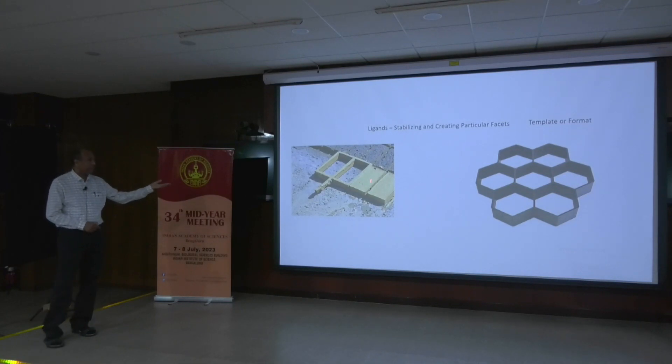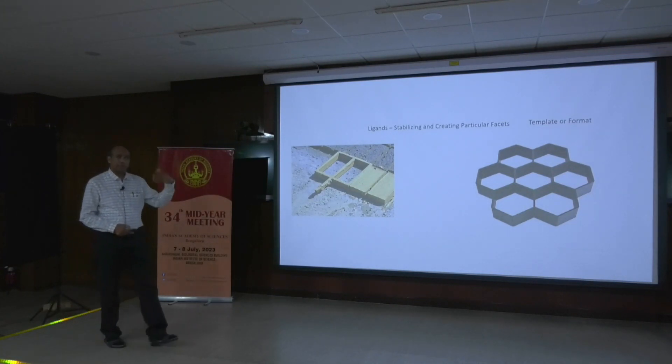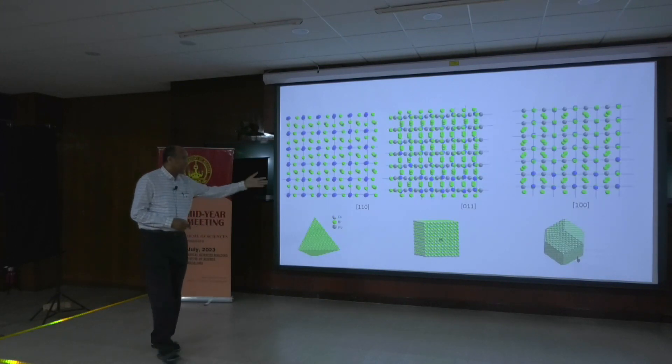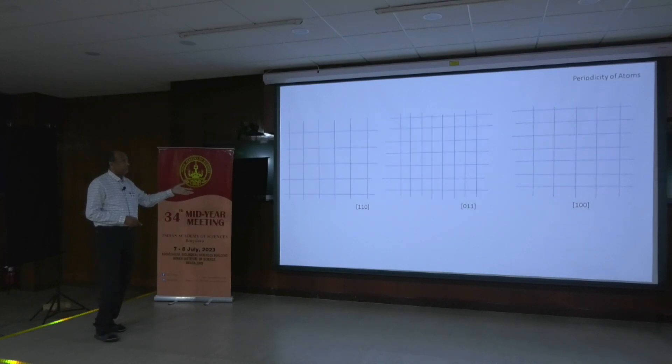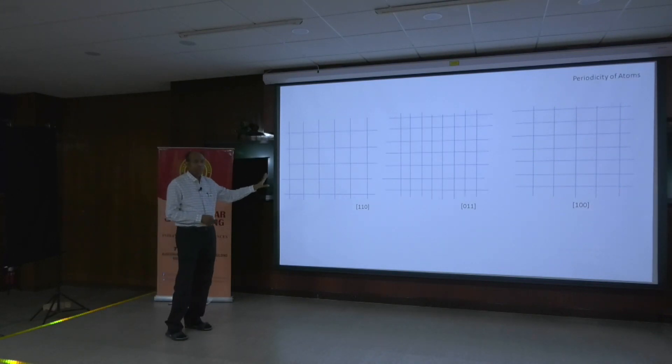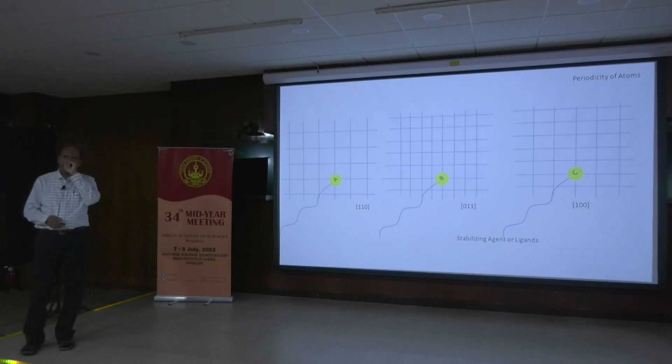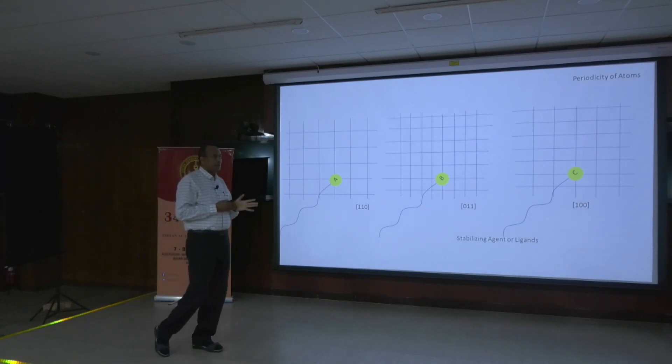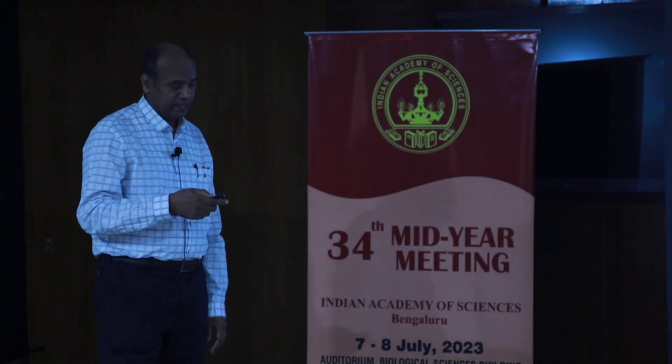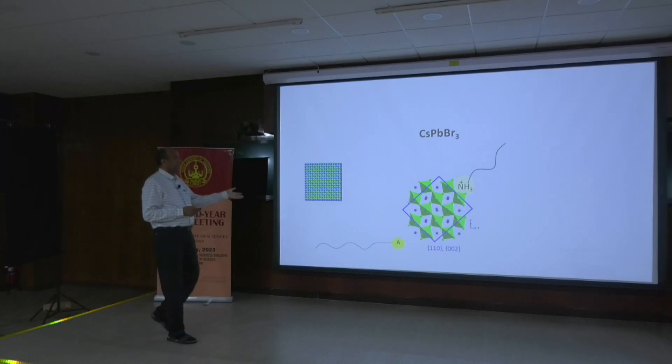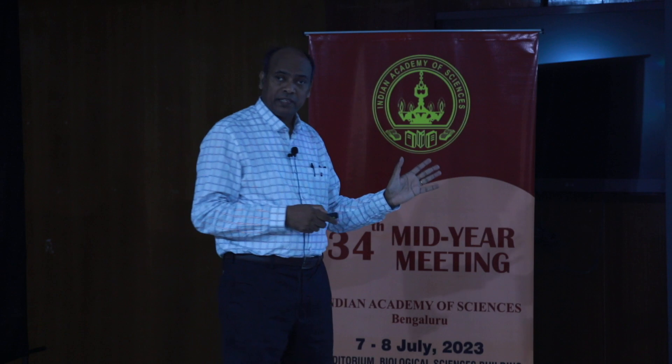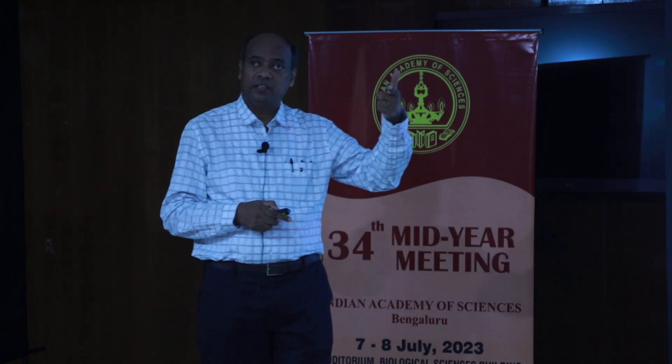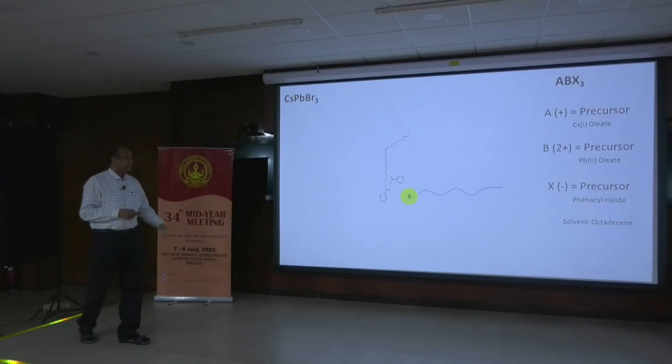It is simple. The ligands can be designed to give different types. I have taken out three facets, and I am taking just the skeleton of the covalent system, the lead one. I am preparing ligands in different sizes. But in contrast to existing nanosystems and quantum dots, these are ionic, but the surface is positively charged. The ligands are positively charged, not like zinc oxide or zinc sulfide, which are negatively charged. We took whatever cubes were existing - maybe 4000 papers came out till then - everything coming out as cube crystals, hexahedrons with single facets. We generated other crystals with different ligands.